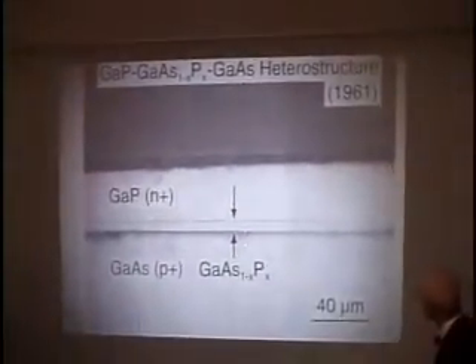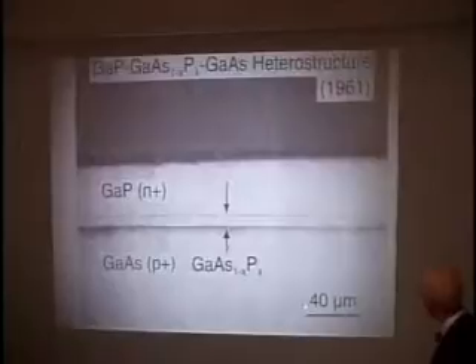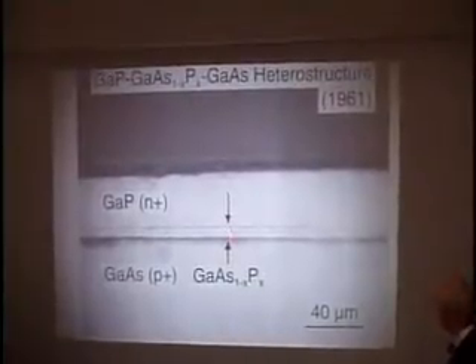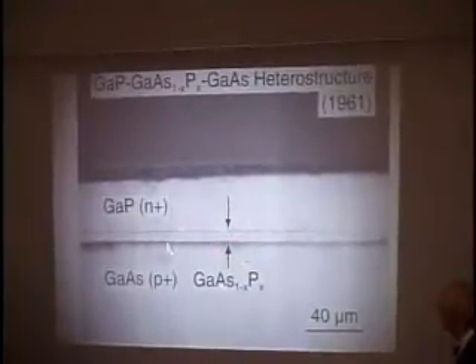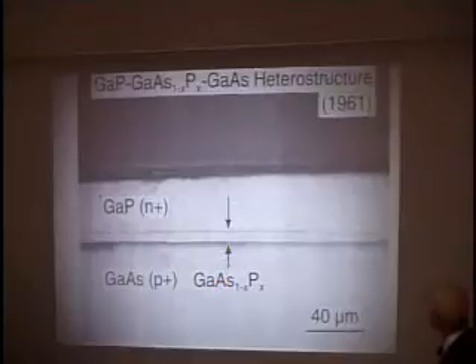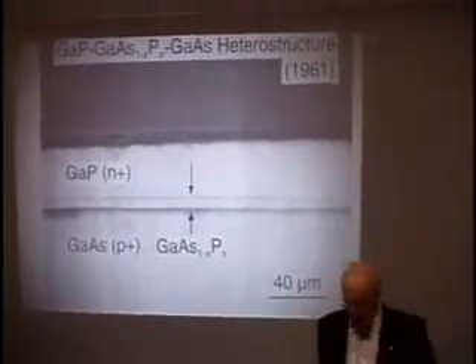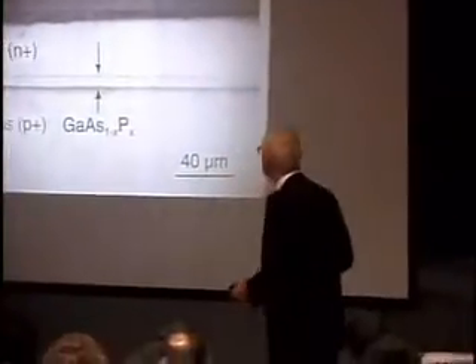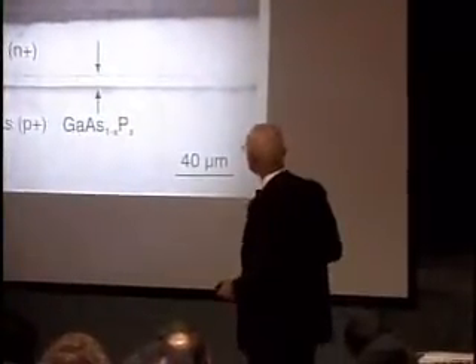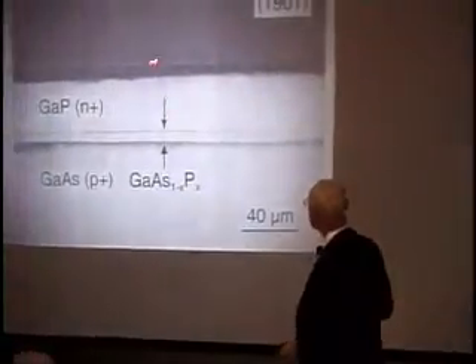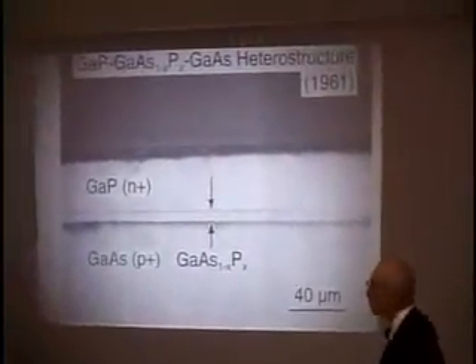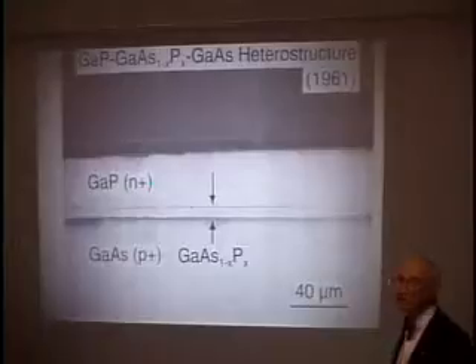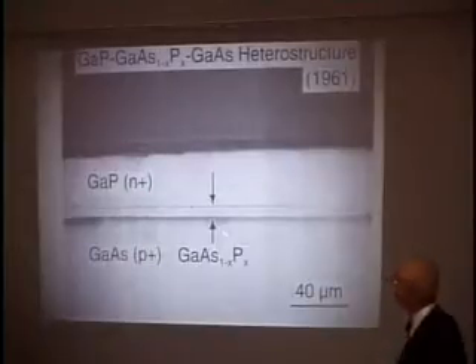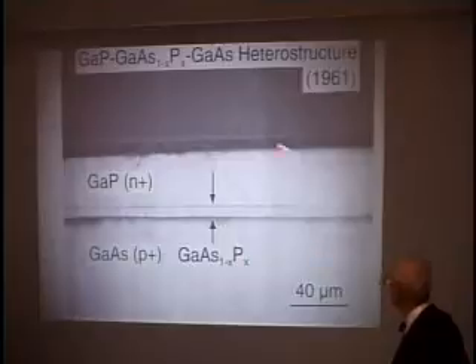And then here is something that I showed you on the diagram. Gallium phosphide grown on gallium arsenide. There's an intermediate gallium arsenide phosphide layer in here. In other words, we know about alloys. And I want to point out something further. I'm a junk collector, so this is in my junk. And this cross-section was done in 1961, but my graduate student photographed it again in 2001. You're looking at a photograph made 40 years later. It was made in 1961 once, it was made again in 2001.